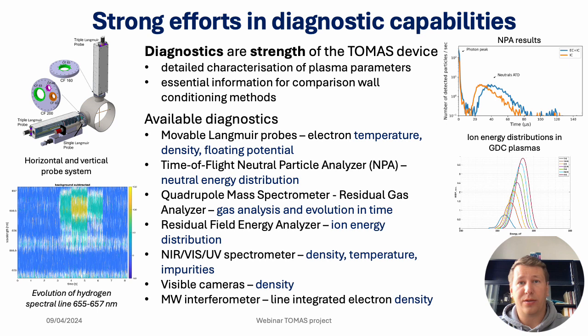As we already mentioned, the TOMAS device is equipped with various diagnostics providing experimental flexibility for wall conditioning studies. Among the diagnostics, we have movable Langmuir probes allowing for measurements of electron density, temperature, and plasma potential along the radius in horizontal and vertical planes, a time-of-flight neutral particle analyzer capable of obtaining thermal and charge exchange neutral particle energy spectra, a quadrupole mass spectrometer providing residual gas content and time evolution of impurity concentrations,